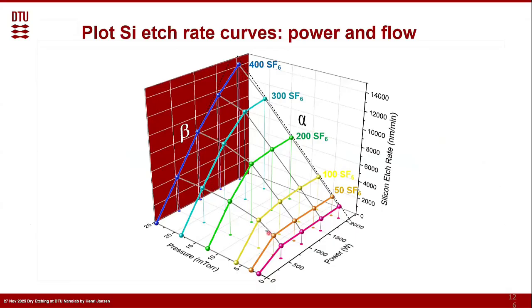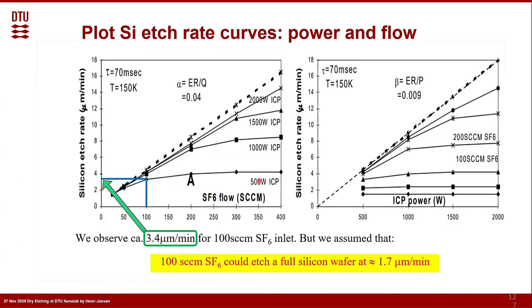Because if you go here and only keep your power at 500 watts, it starts to saturate. So somewhere here you have a lot of flow, but you don't use it. And if you go along this line and say, I fix the flow, then you use a lot of power, but uselessly. So you want to be somewhere where both of them still have an effect, and that line is the maximum of our performance. Is it correct? Yes. Good.